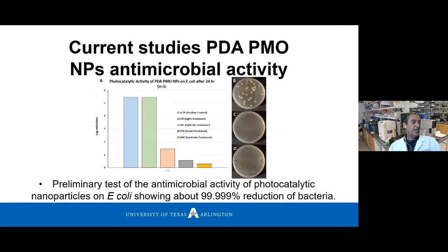After this experiment, we still had to answer the question, okay, is this going to work on bacteria? So in our next experiment, we did the same thing. We exposed E. coli to our nanoparticles in a suspension. And we found, in this preliminary antimicrobial test, that the nanoparticles were able to eliminate 99.999% or a 5 log reduction of bacteria, which is really good because the results for our nanoparticles were basically the same as the positive control, which was bleach added to the bacteria.